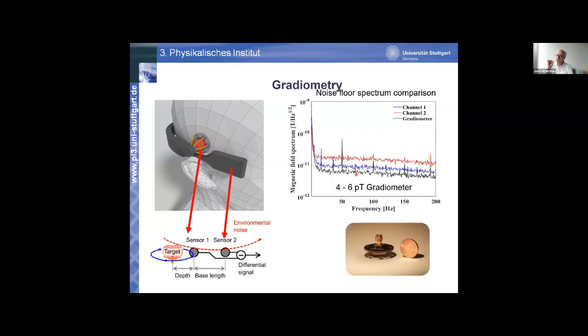All right. And one key feature to achieve this is that our sensor sizes are getting small. So here you see a rather new compact version of these. This is a diamond sensor where the diamond is somewhere in between here. You see a mounting plate and a bit of an electronics component here. And the one thing you would need in addition to what is already in here is microwave, and it has the size of 1 eurocent. And you can shrink this down, if you put in a bit more sophisticated optics, also down to 1/10 of that size. And this allows you really to do point-wise measurements at the site you're interested in, this reddish site, or a few centimeters away.